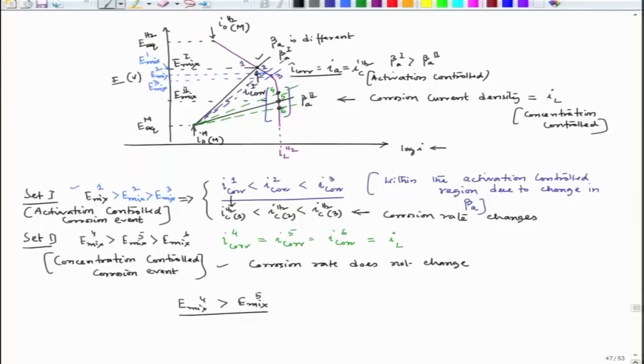Of course, in the set 1, place 1, 2 and 3, if we compare 1 and 2, the 1 has got a higher corrosion potential than the 2. So, since 1 has higher corrosion potential and at the same time that metal polarization line is cutting the hydrogen polarization line at a lower corrosion rate, here ennoblement is taking place, and at the same time ennoblement leads to decrease in corrosion rate of that metal. But in the set 2, even if ennoblement takes place, corrosion rate does not change. So, we have to be very careful while considering corrosion events, and we have to understand the polarization graph very carefully. So, we will talk about polarization curve in the next lecture. So, let us stop our discussion here. Thank you very much.